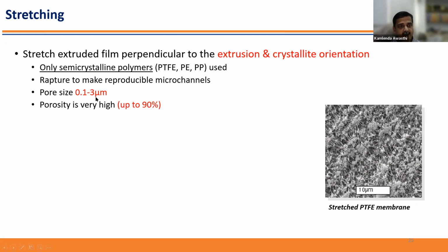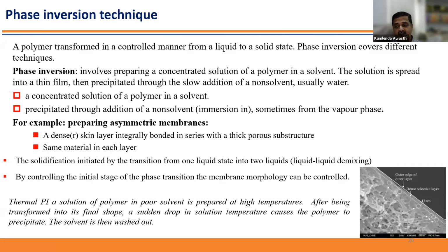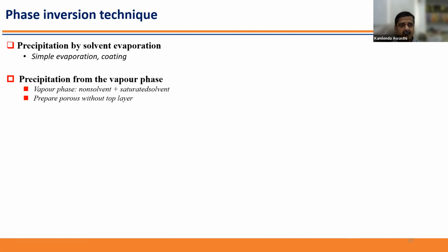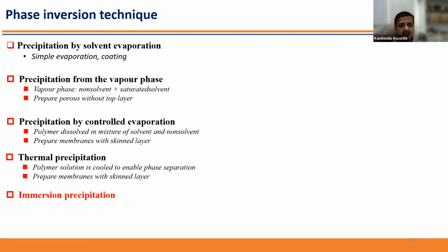Porosity is very high, and the pore size is very large here. Then the phase inversion technique can also be used to make an asymmetric membrane. Here we have a solution of polymer in a poor solvent prepared at high temperature, and when we transfer it into its final shape, there is a sudden drop in temperature so that the polymer precipitates and the solvent passes out. This is basically simple, but there are some constraints with phase inversion. There is precipitation by solvent from the vapor phase and so on, and we can also have immersion precipitation.